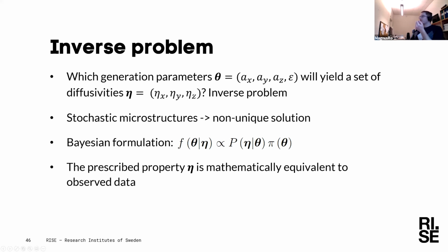And we have that information in 3 directions. So this is a difficult inverse problem, and it doesn't have a unique solution, because these structures that we simulate, these virtual materials we simulate, they are stochastic by nature. So we do a Bayesian formulation where we treat the prescribed property, which is this vector, as data. And we look for a prior distribution, a posterior distribution of these generation parameters given the data.